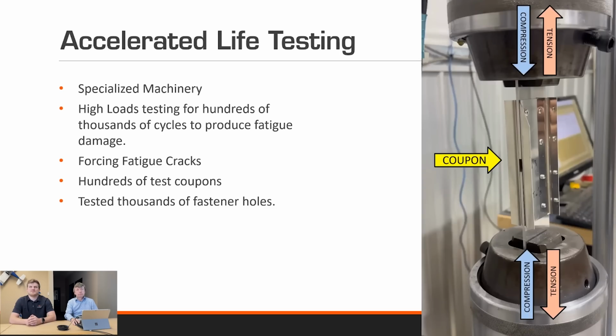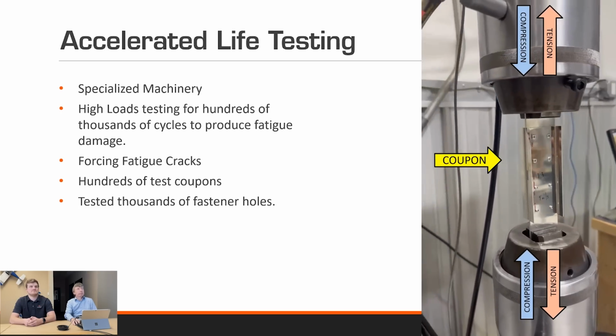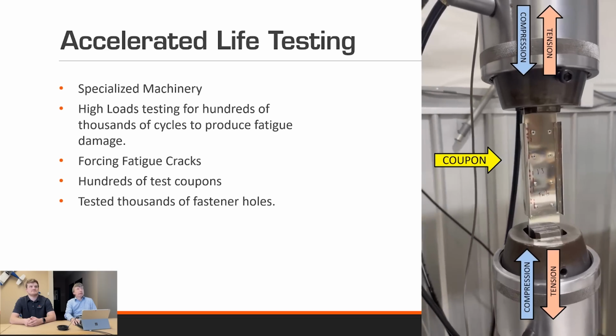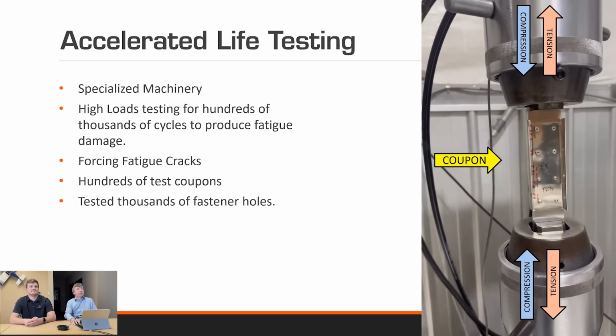Accelerated life testing is really based on a small coupon level, really testing the details of these components. They're done with high loads for hundreds of thousands of cycles so that we can produce statistical data sets that force fatigue damage and create fatigue cracks, and then we can make comparisons among different variables, methods, thicknesses, etc. We're just showing you a coupon running in our fatigue test machine there. This video runs. It's a machine that pulls in tension and compression.